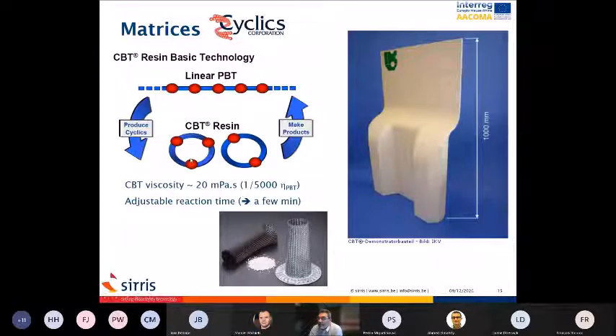When we are talking of this example of cyclic product, we can see that when we want to process it by chemical reaction, we reduce it to monomer or oligomer, very, very short length molecular systems that are very fluid. The viscosity of this CBT chain could reach more or less 1/5000th of the value of the PBT, which is the linear recombination of those molecules. So in this way, it's possible to flow the product, the matrix, into the dry reinforcement network. And we can adapt the reaction time by playing on the chemistry of those materials, and also with the temperature.